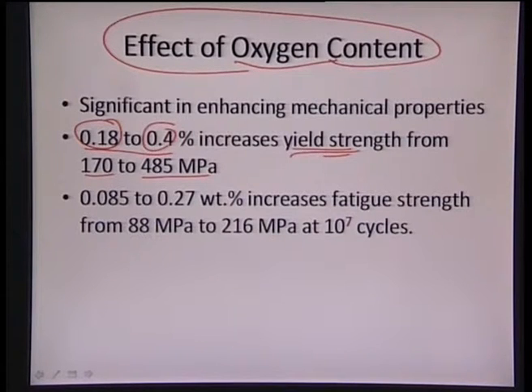At the same time, if we increase the oxygen content from 0.085 to around 0.27 weight%, we will also see an increase in the fatigue strength. So we see that fatigue strength is increasing approximately from 88 to 216. So if we increase the oxygen content approximately to double or triple, the same type of effect we can see in the fatigue strength as well.